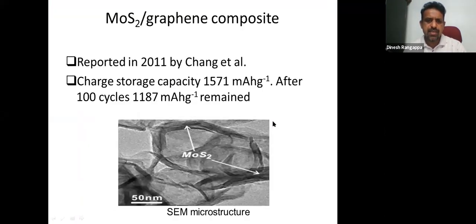Okay, this is another important thing I would like to mention here. Recently, there is a lot of progress in making graphene and other metal oxide and metal sulfide nanocomposites to increase the capacity of electrode materials, as anode materials. This is one example reported in 2011 by Chang et al.: molybdenum disulfide and graphene composite, and it shows a charge storage capacity of about 1571 milliampere per gram. After 100 cycles, 1187 milliampere per gram was achieved.